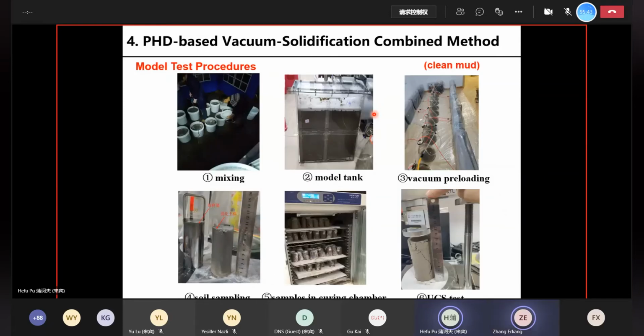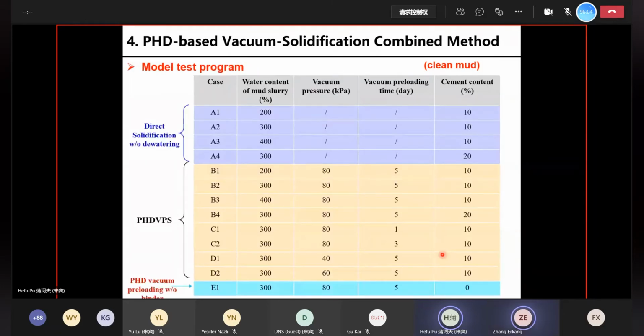This is the test procedure. Again, we first mix the slurry and place the slurry in the model tank. Then we start the vacuum preloading, and after that we take out the soil sample and cure the soil samples in a curing chamber, and after that we take them out for other testing. This is the model test program. We have 3 series of tests.